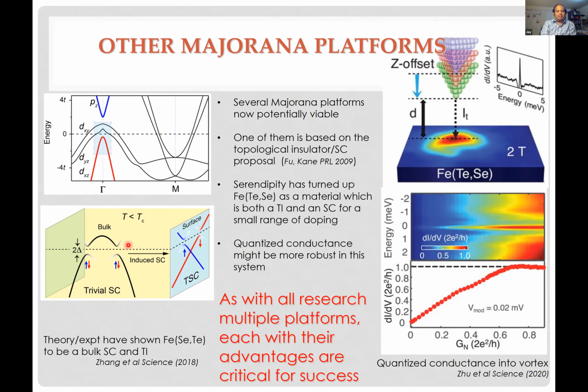And then the prediction is that when you have a vortex in this superconductor, you would have a Majorana mode that you can tunnel into with the scanning tunneling microscope. And this was seen, and actually this shows very nice quantized conductance. Okay, this is the weird part. Only 2 of the vortices out of like 20 show quantization, but nobody shows more than quantization. So it's an intriguing avenue.